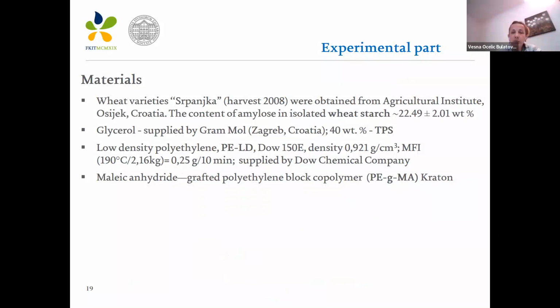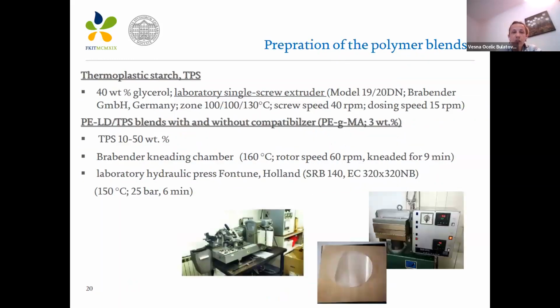We use wheat starch that was plasticized with glycerol. The amount of glycerol was 40%. This is the preparation of our polymer blends. First of all, we have to prepare the thermoplastic starch with glycerol, and then we prepare the blends with and without the compatibilizer. The proportion of thermoplastic starch was from 10 to 50%.